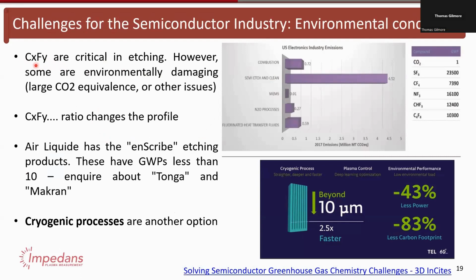So obviously, these CF gases are quite critical for etching, but they're quite environmentally damaging. If you look over here at the global warming potential, CO2 has a potential of 1, but SF6 is 23,000, CF4 is over 7,000, C4F8 is 10,000. So they're really very environmentally harmful, and we do want to get away from them where possible.